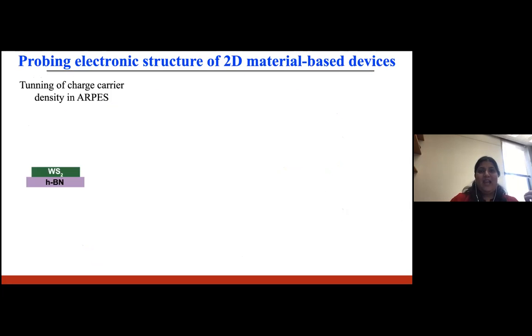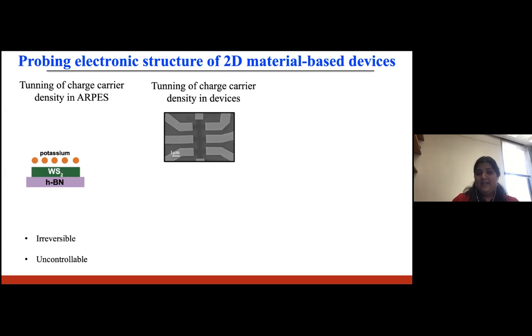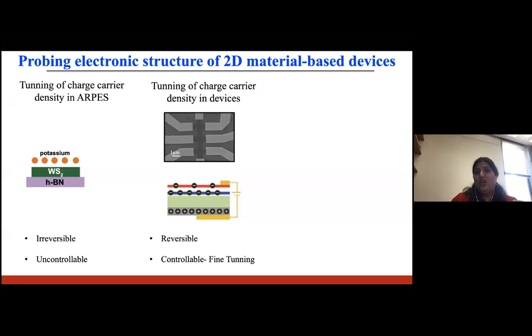Okay, so I just showed you that in ARPES, we can tune the Fermi level by alkali metal doping. This is great, but this process is irreversible and uncontrollable. And the added atoms can cause impurity scattering, which can result in increased measured line widths and make it difficult to separate from the intrinsic effects or intrinsic interactions. And we know from the transport measurements that in devices, we can tune the charge carrier density in a non-invasive way by using electrostatic gating. This process is reversible and we have much better control.